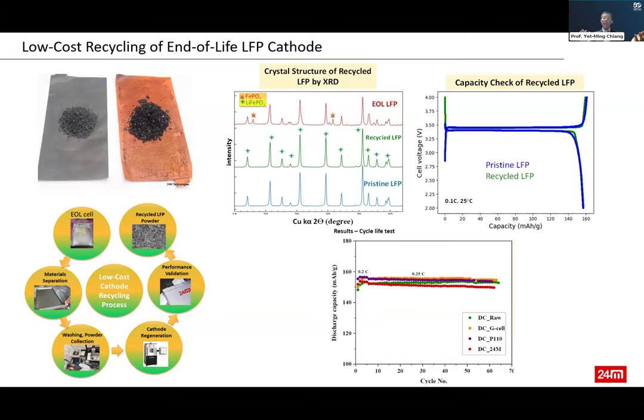However, it's possible to fix that. So with the graphite, for example, that lithium carbonate is soluble in water. It can just be rinsed, right? With the LFP, you can restore that lithium with, for example, a low temperature roasting process with lithium carbonate. You can restore that 15% or so of missing lithium. If you do all that, you get the results that are shown here. What we've shown is that you can take that LFP essentially back to the same performance as the starting pristine LFP.